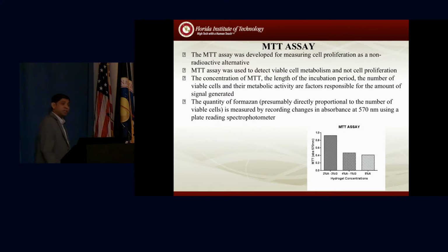And we also do MTT. One of the reasons we did MTT is that we want to optimize our alginate gelatin concentration, because MTT will give you the metabolic assay. So we have been trying to optimize it. This was a sample of how you optimize the different alginate gelatin concentrations, which people have actually used, and try to see what may best fit in terms of viability for our applications.